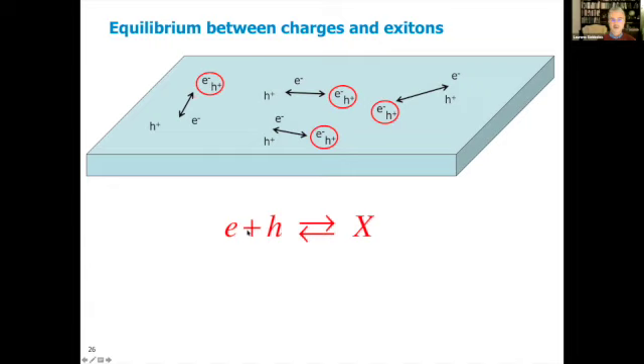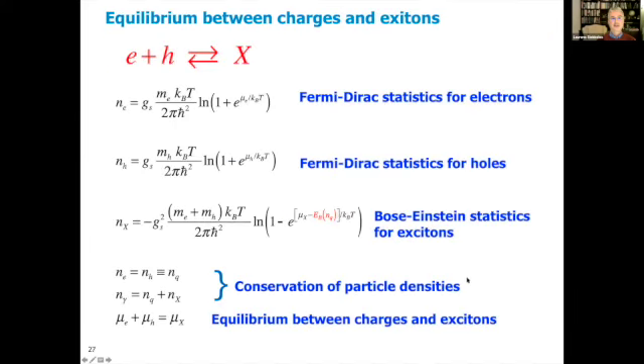So you have an electron and a hole, they can recombine to form an exciton, and in turn there can be thermal dissociation of the exciton into free electrons and free holes. Now we work this out using statistical thermodynamics. The density of electrons in a two-dimensional material is something with the effective mass of electrons, and there's the chemical potential over kT of the electrons, a similar expression for the holes, and this is Fermi-Dirac statistics.